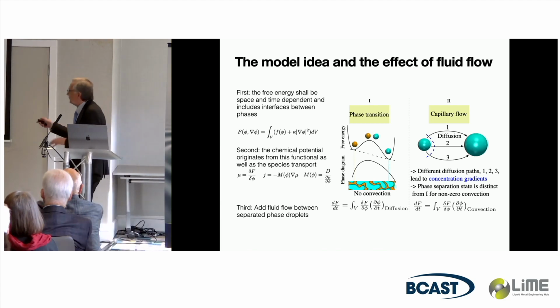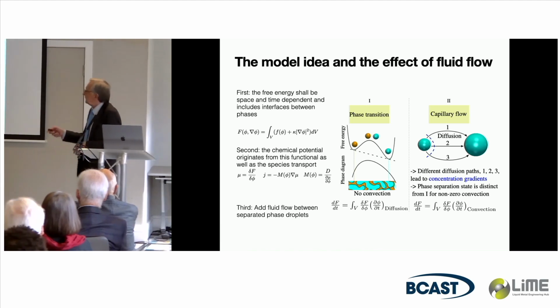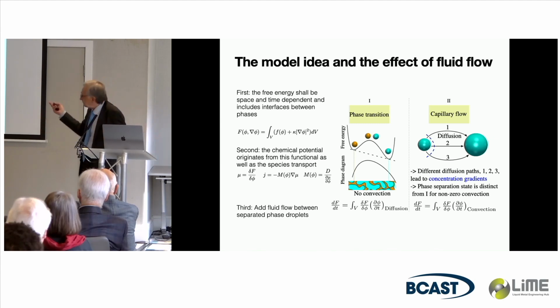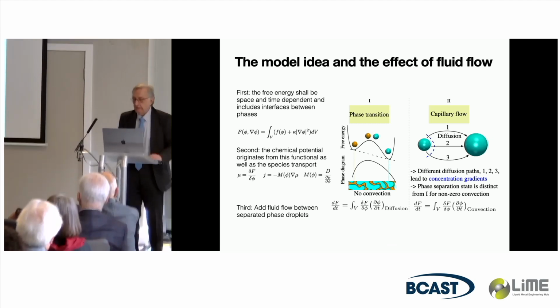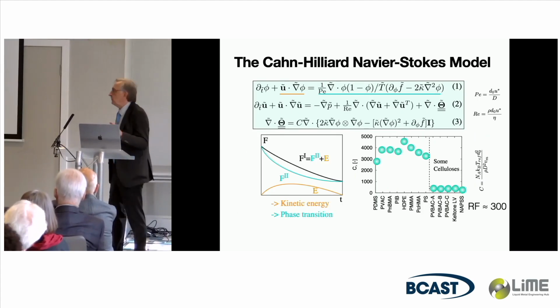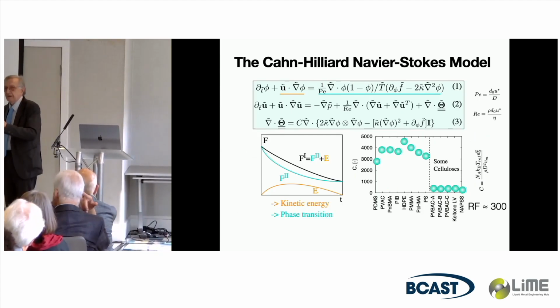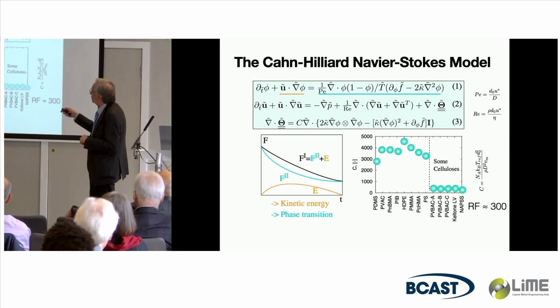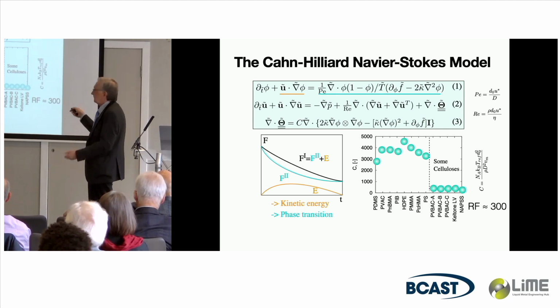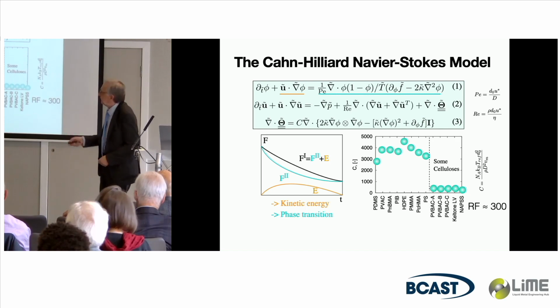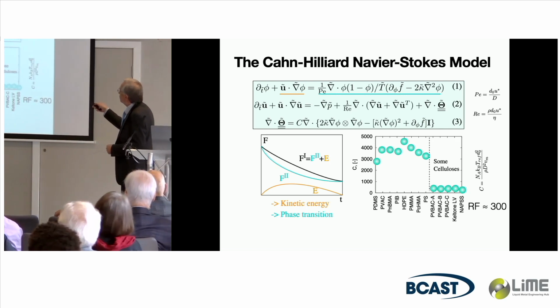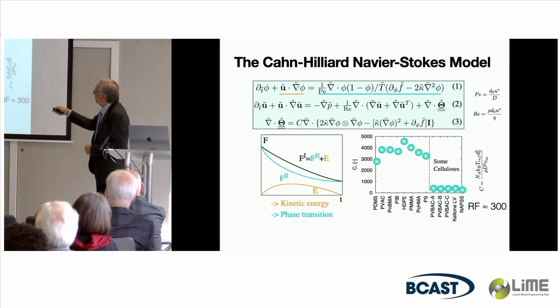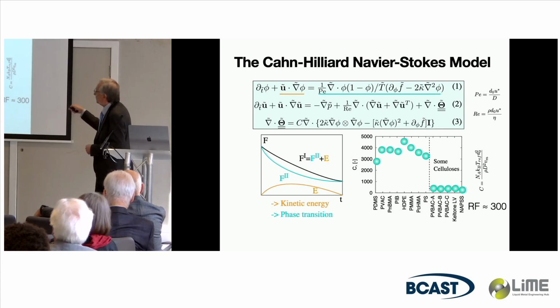So what we did, with the colleagues in Karlsruhe, is phase field modeling, what else? With convection, that's it. And you have to take that into account. So don't be worried about these equations. The only important point is this term here. You combine it with the Navier-Stokes equation, you have an advective term here, the rest is standard. You read in textbooks on the Cahn-Hilliard equation. Besides this point, here is the standard Navier-Stokes equation, and you have to add an additional term